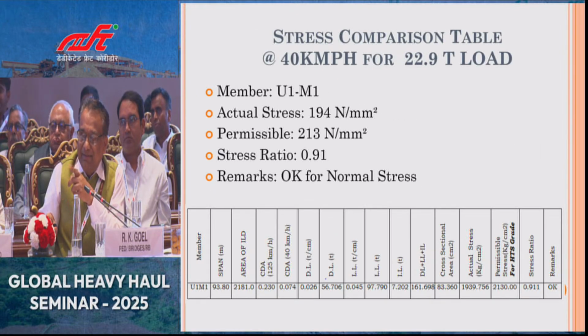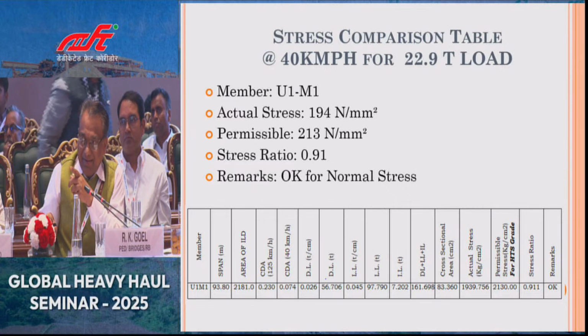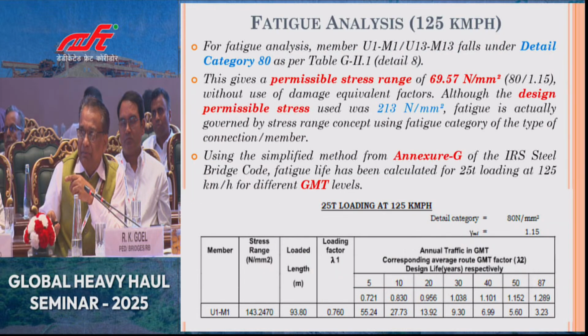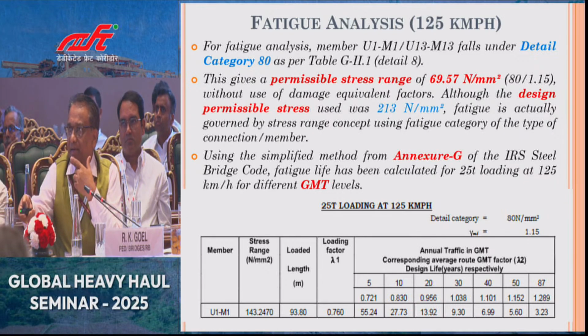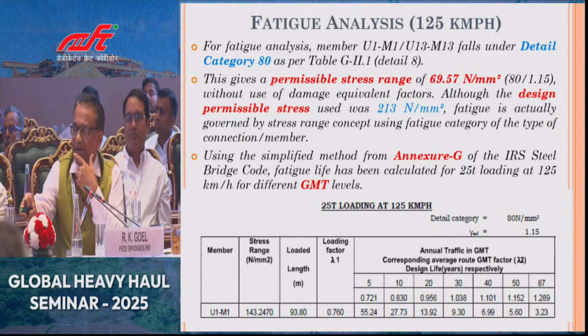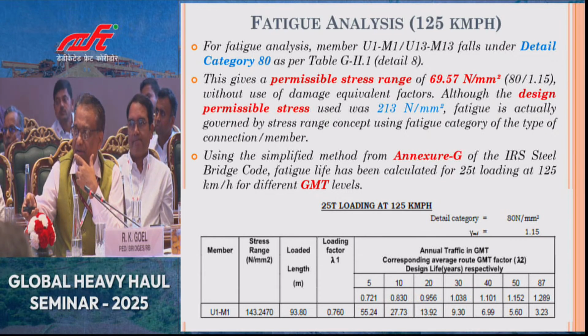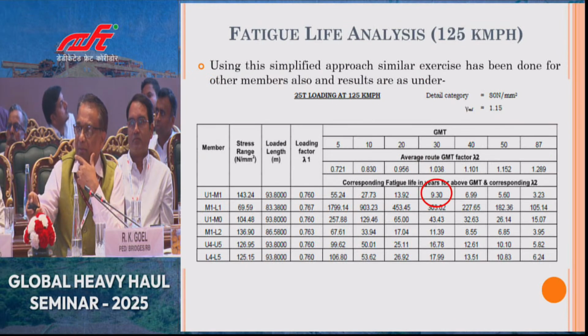So we did the reverse analysis to find out the actual residual fatigue life of this member. If we do the reverse analysis by using the present day codal provisions, taking a detail category of 80, if we take average GMT of 30, then the residual fatigue life of this member was coming out to be 9.3 years. And for other members also we have calculated. Some of the members were having a residual fatigue life of more than 300 years. And the other M1, L2 member was also having a residual fatigue life of 11.39 years.